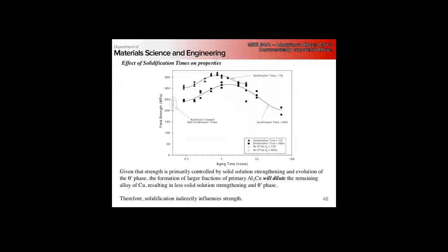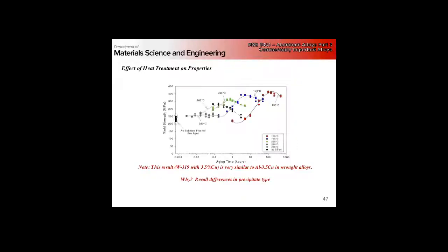It's aluminum, copper, silicon, so it's going to age. And it ages differently based on the different heating rates. We've got two mechanisms going on here: solid solution strengthening and the evolution of the phase. There's a trade-off here. As we nucleate more precipitates, we reduce our solid solution strengthening effect. The slower we cool it, the larger the primary regions are, the larger fractions of the dendrite regions. We have less copper available in the other regions of the structure to give us strengthening. So this solidification indirectly influences strength.